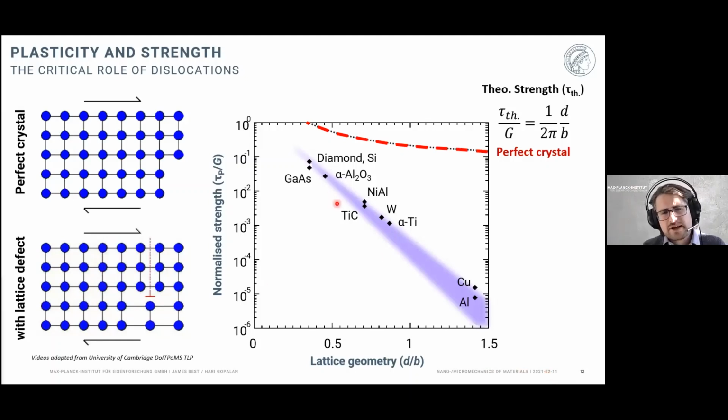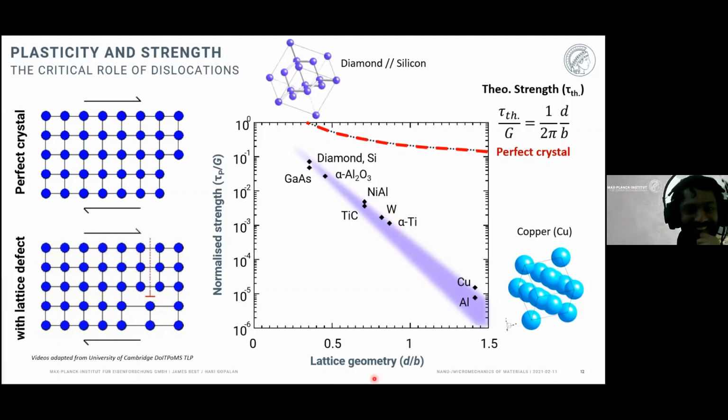Right. And so why do we see these differences when we go back from rugs to crystal structures? As mentioned, this is because of the geometry. So we see this relationship between the strength and the geometry, and that for harder materials, that is to say materials like diamond or silicon, we have a much more compact lattice along these slip planes, which means that the atoms are pushed closer together, and it's much more difficult to squish or to slide those relative planes of atoms. So maybe in your analog, Hari, it's like having an elephant sitting on your carpet, which makes it even more difficult to move.